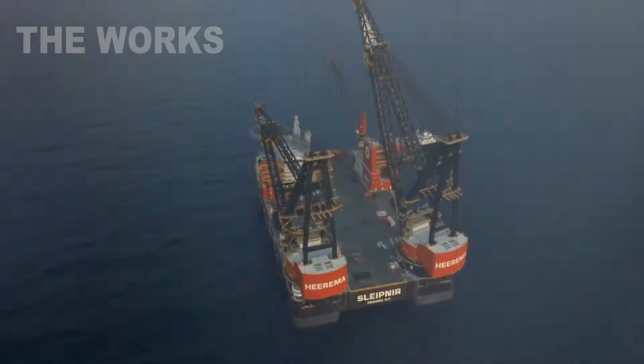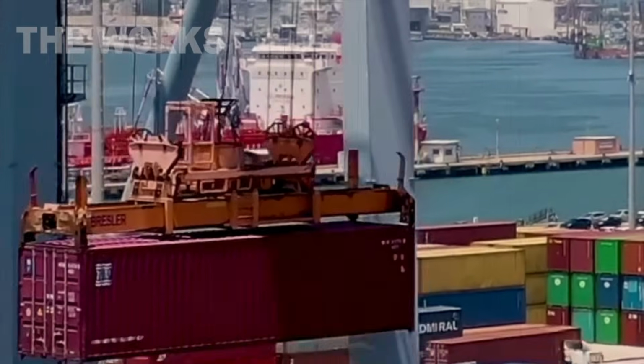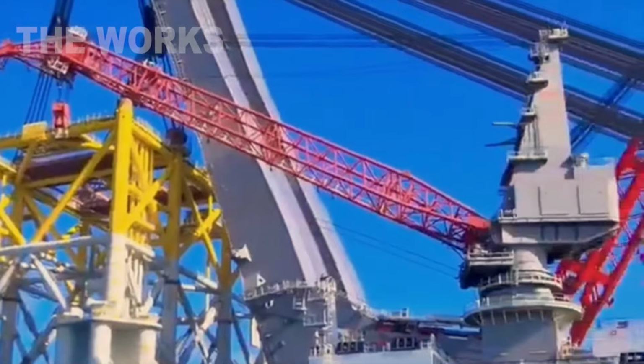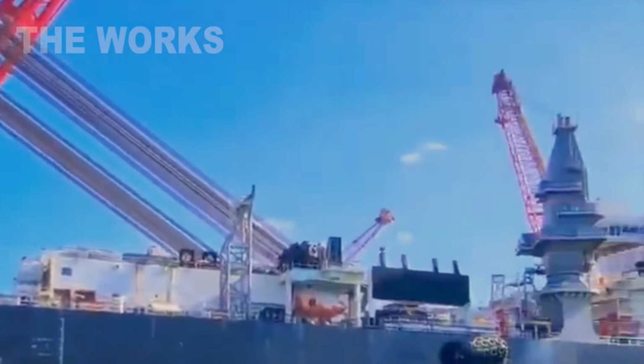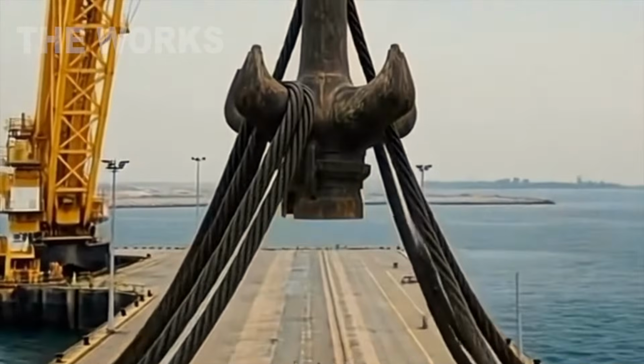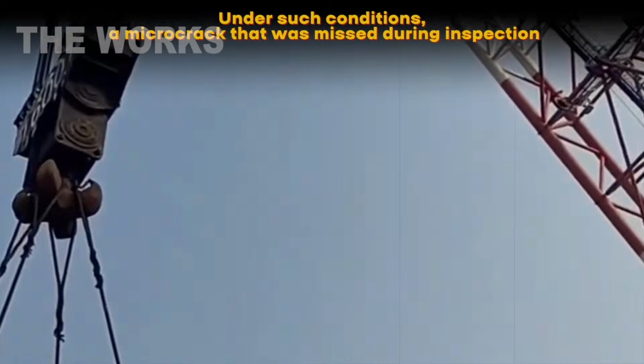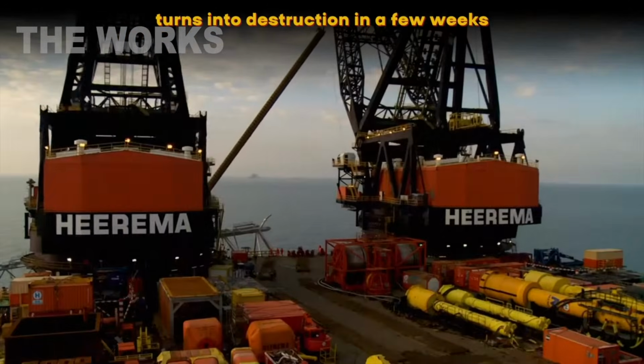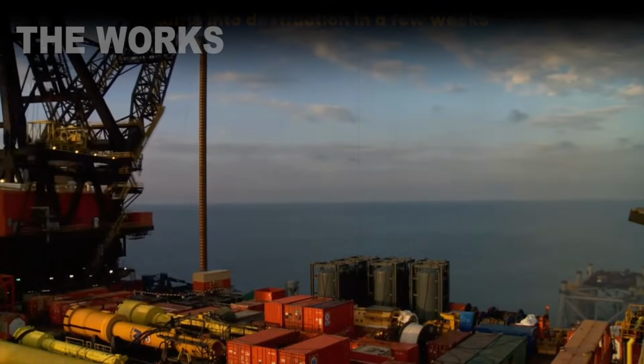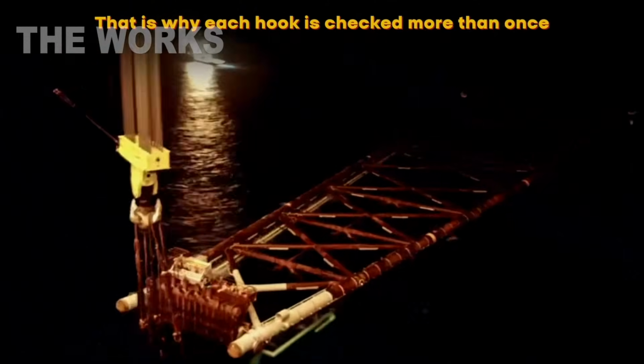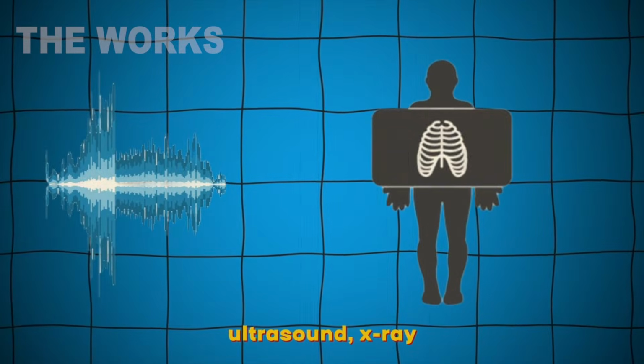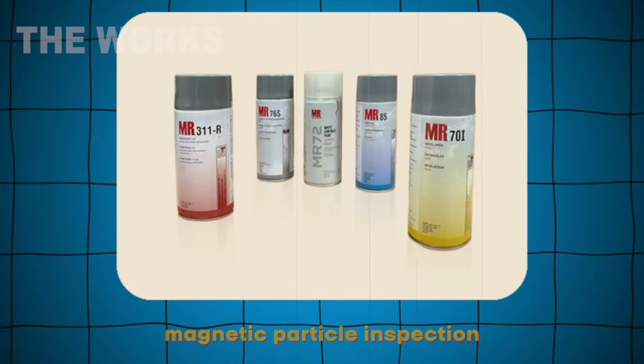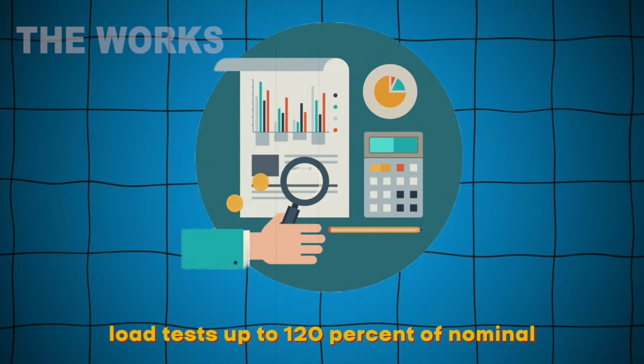These cyclic loads are especially dangerous. They make cracks grow even when the overall stress stays within design limits. Under these conditions, a microcrack that slipped past inspection turns into catastrophic failure within weeks. That's why every hook gets tested not once but multiple times. Ultrasound, X-ray, magnetic particle inspection, load tests up to 120% of rated capacity.